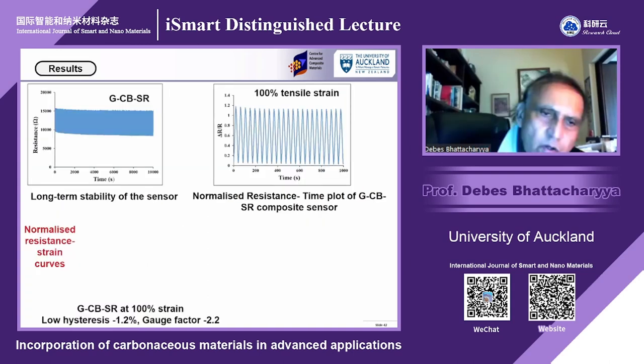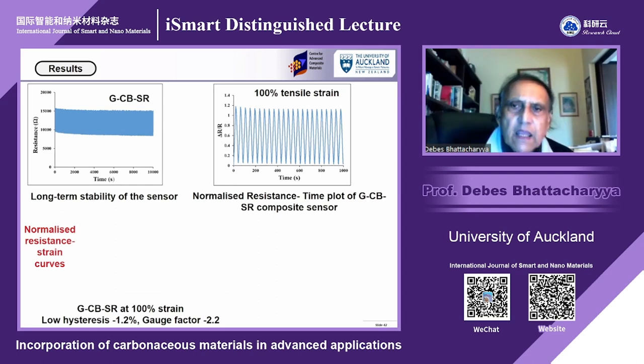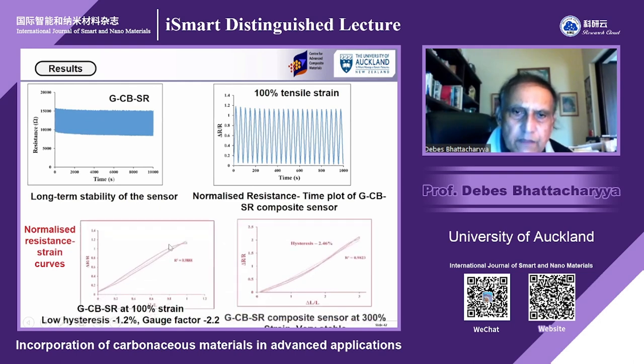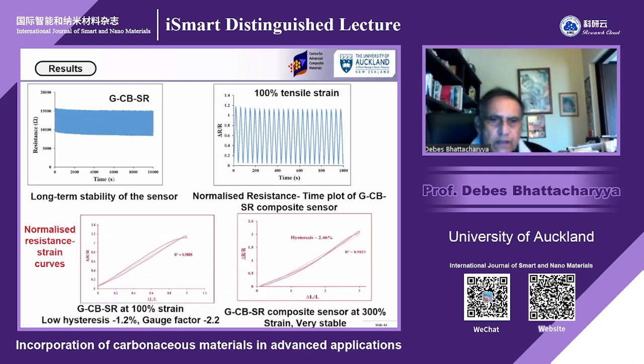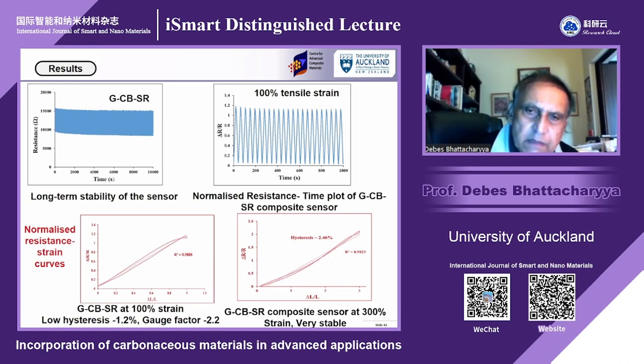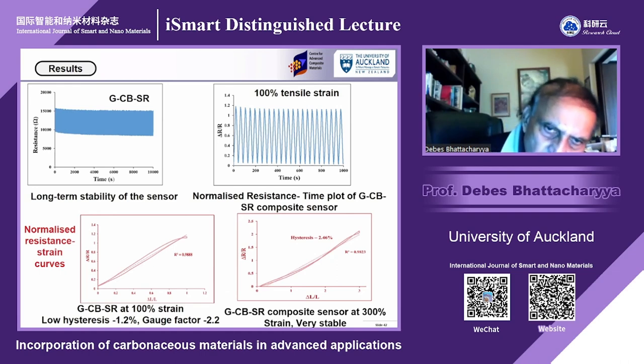When we did that, as you know, all stretching sensors are tested over cycles, so that repeatability is there. I have shown over 1,000 seconds. In her thesis, she has checked 5,000 cycles and 10,000 cycles, and it is pretty stable. You can see the result is reasonably stable over time. So you can see that this did work. With graphene, carbon black, and silicone rubber, at 100% strain and 300% strain, it is very stable. We have used that material for stretchable wearable sensors also.